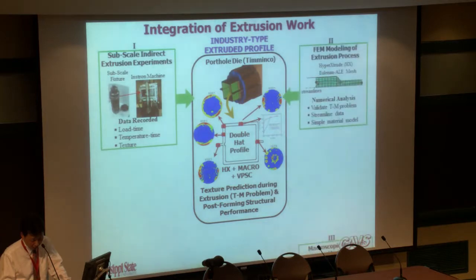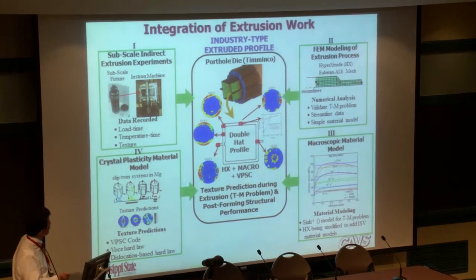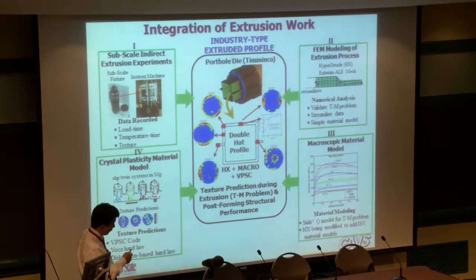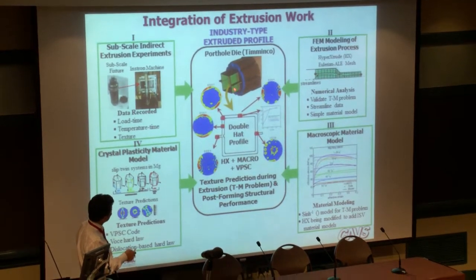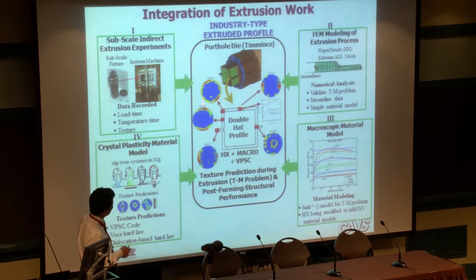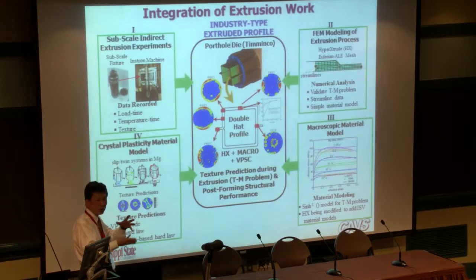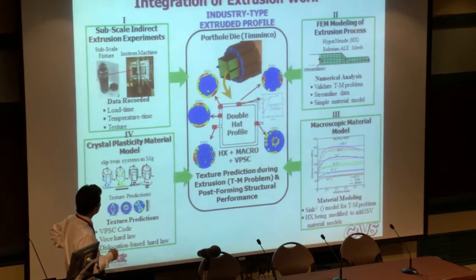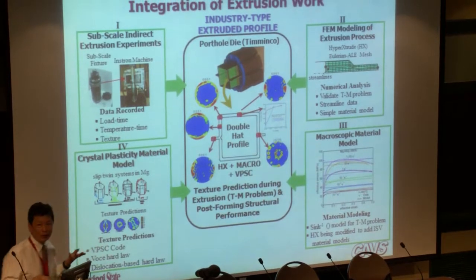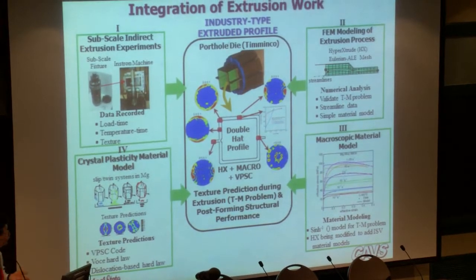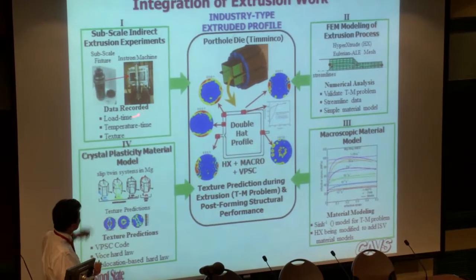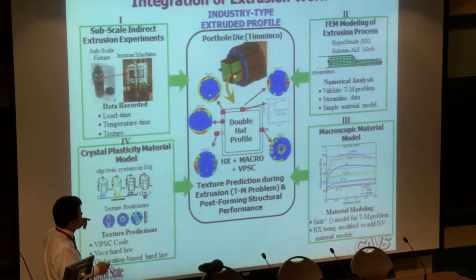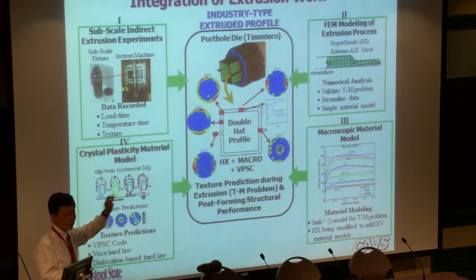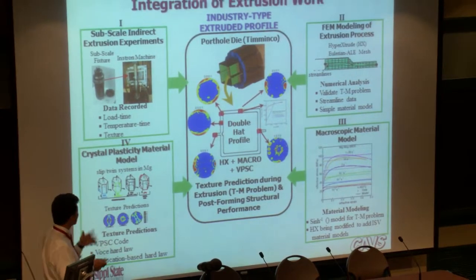And for extrusion, I just want to quickly show you what we're doing here. So extrusion, you have this very complicated thin wall type double hat we call, and they want to predict these textures around different locations, and they don't relate to the yield strength. So what we do was, in the laboratory, we have to be credible to know how we can predict a described extrusion. So in the laboratory, we designed this laboratory will be maybe 1/10 smaller than this, very small. But you still have a gradient structures.